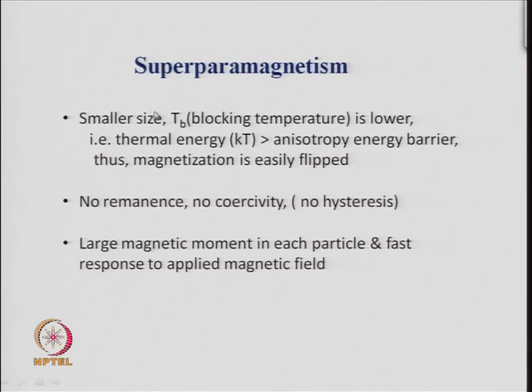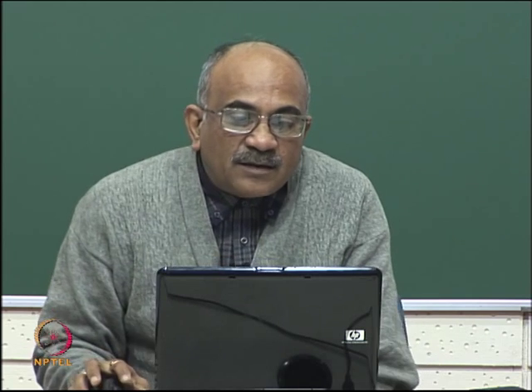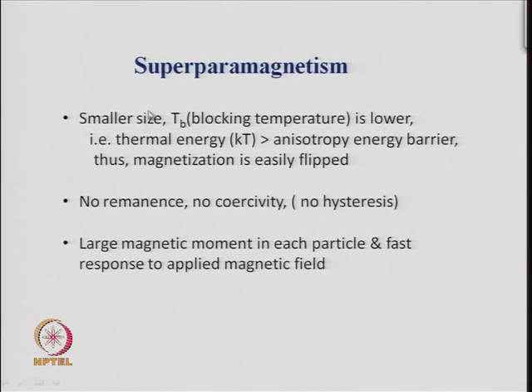Now, in superparamagnetism, the smaller the size, then you have a temperature which is called a blocking temperature. That means that as you are lowering the temperature, the magnetization should increase in a paramagnet, like in any ferromagnet also, the magnetization increases as you are lowering the temperature, but in a superparamagnet below a certain temperature, the magnetization will start decreasing. Now, that temperature is called the blocking temperature. So, the blocking temperature changes as a function of size. The smaller the size of the particle, the smaller will be the blocking temperature.